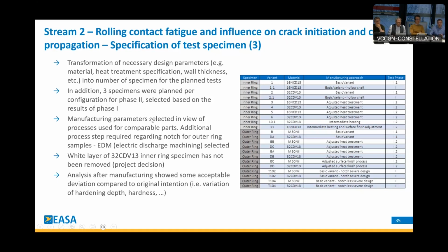Manufacturing parameters mentioned before already, selected in view of processes for comparable parts, means standard aviation. But we needed an additional process step for the notch that was mentioned to ensure that we have the good, let's say, ovalization, the body stress, and so on. And therefore, we selected EDM, electric discharge machining. One remark here, the white layer of the 32CDV13 inner ring specimen has not been removed. But this was a project decision based on some aspects that were discussed in the project team. And of course, as all of us know, in manufacturing we sometimes have a slight deviation, a little bit outside on this side or a little bit too low, but all of these deviations were acceptable and were checked and had no impact on the test results.